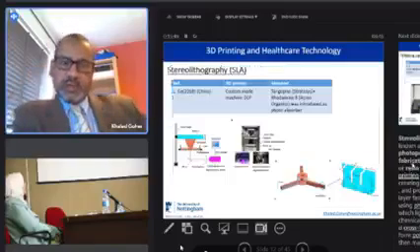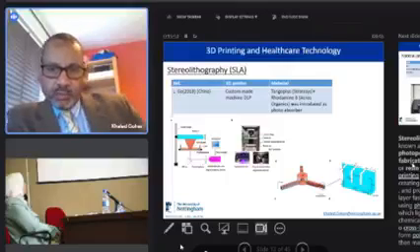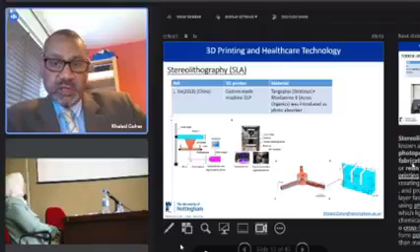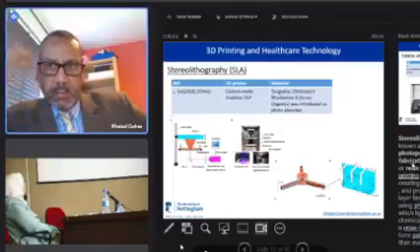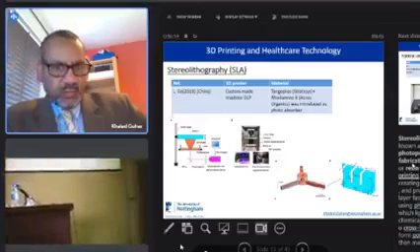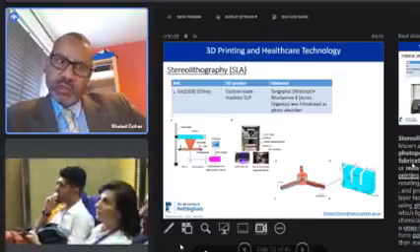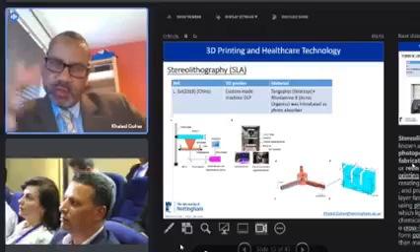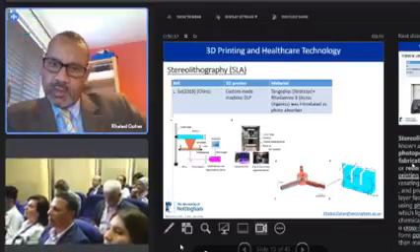Stereolithography is a more expensive type of technology. SLA, vat photopolymerization, or optical fabrication, or photosolidification, is resin printing. These are all different names for the same technology, SLA. More expensive to run, with expensive machines. The resin itself is more expensive, probably 1 liter of resin between 150 and 250 British pounds. More expensive to run, but it will give you more flexibility in terms of 3D printing different types of material, ranging from rigid resin to soft materials.